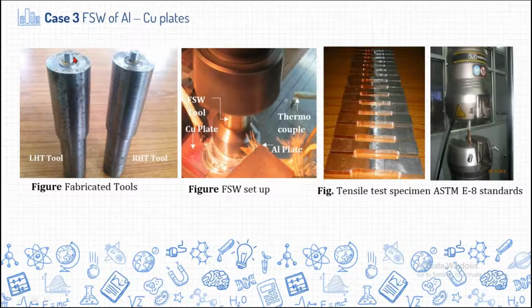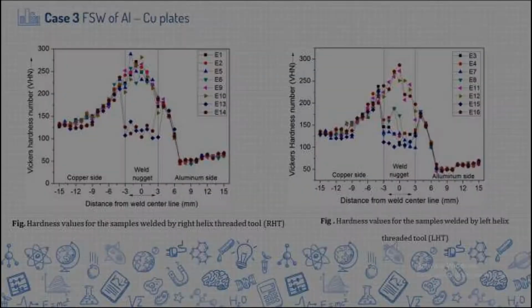As this copper material is comparatively harder than aluminum, we wanted to have a threaded tool so that mixing takes place in a good way, and we conducted the samples. These are the thermocouples. We wanted to record the temperature obtained from the weld plates, so inserting a thermocouple and connecting to the data logger, we recorded the temperature obtained by using this friction stir welding process. These are the various tensile samples after conducting friction stir welding.